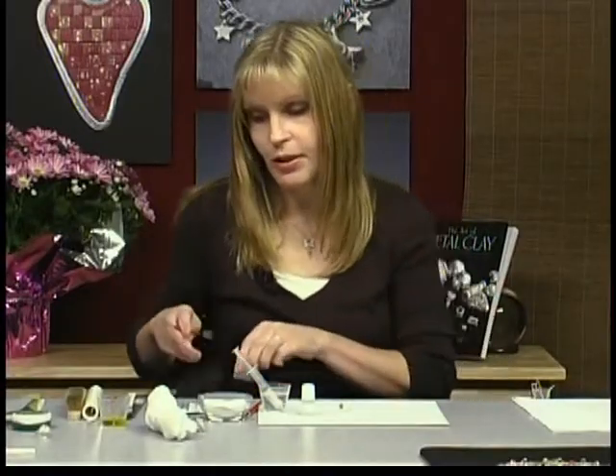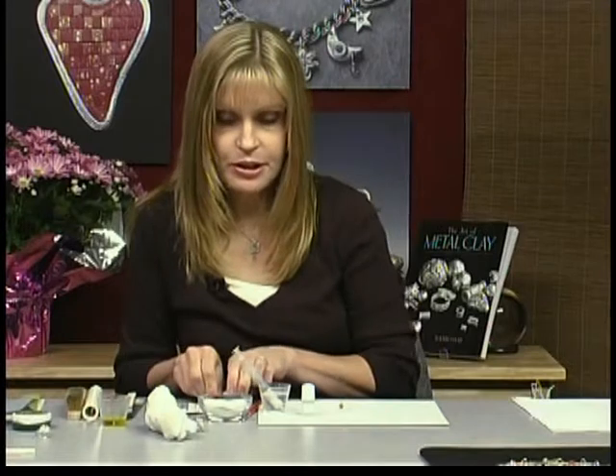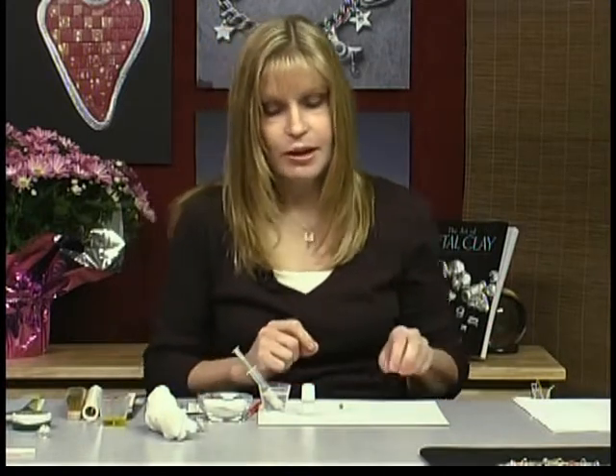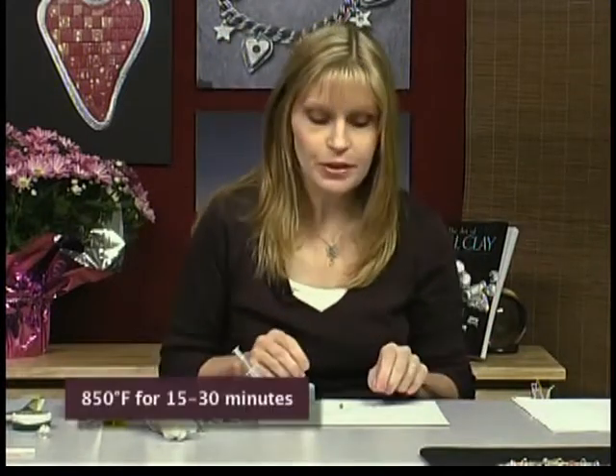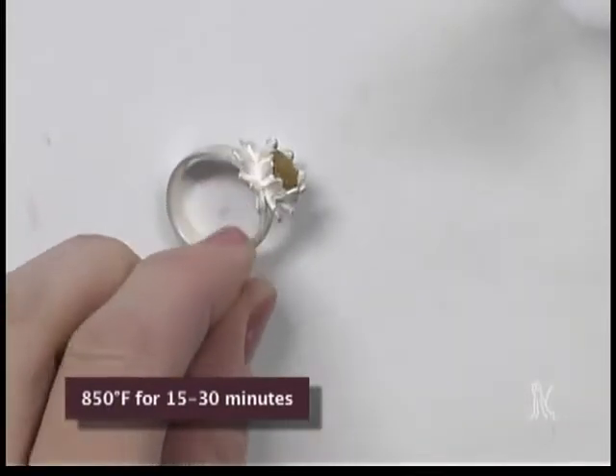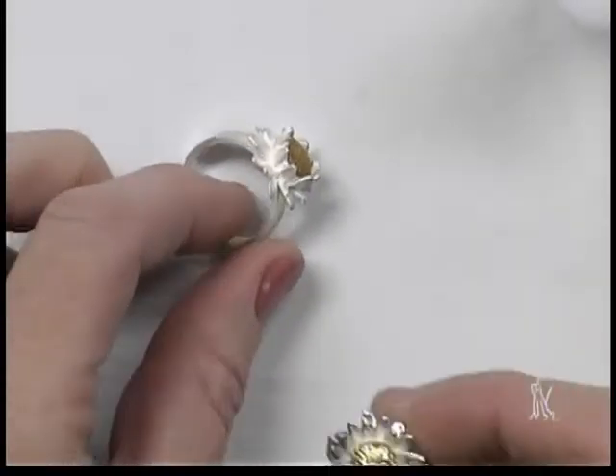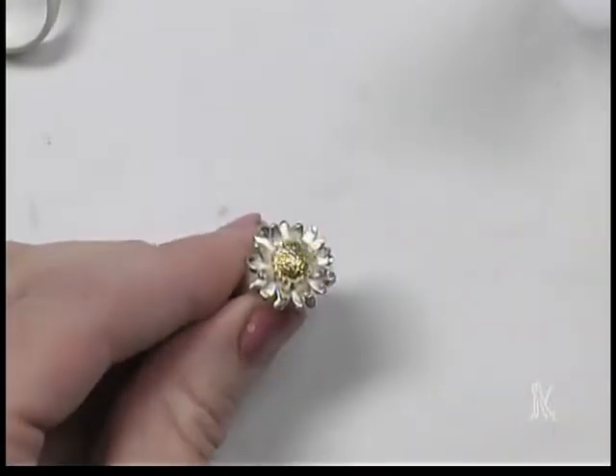Now after I've applied 2 other layers for 3 total, then you will put this back in your kiln, or you can torch fire it, and you want to fire it at 850 degrees for no less than 15 minutes. And that will bring out the gold. And I've got a finished one here.